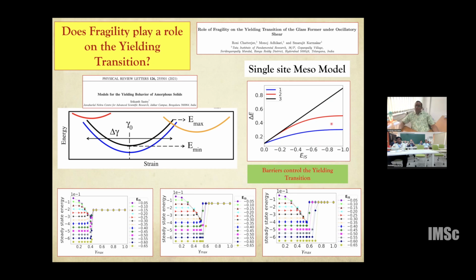And if you use this information in this mean field single site model and repeat the calculation to produce the steady state phase diagram of oscillatory shear, we find that when you take a liquid whose barrier doesn't grow beyond a certain value as you do better and better annealing, you get a phase diagram where the yield point does not move anymore. But if you take a glass modeled by this black curve, where the energy barrier grows with annealing history, then you get a phase diagram where you can clearly see that the yield point systematically moves to higher and higher strain. This suggests that while modeling this kind of materials at a coarse grain length scale, one must include this information of barriers and how they evolve with your annealing protocol.